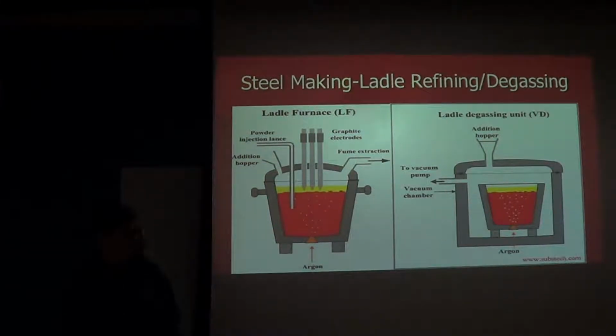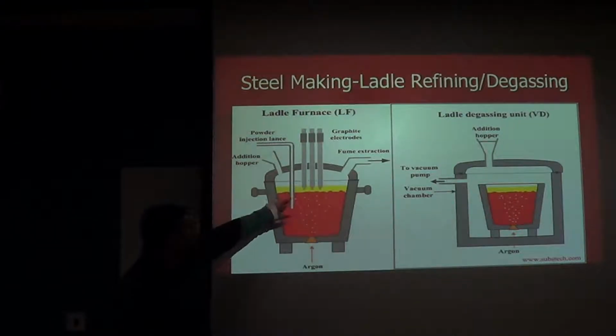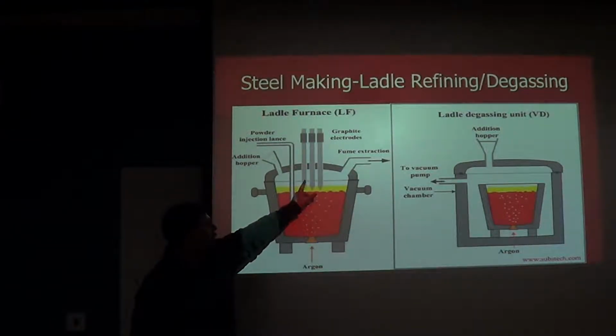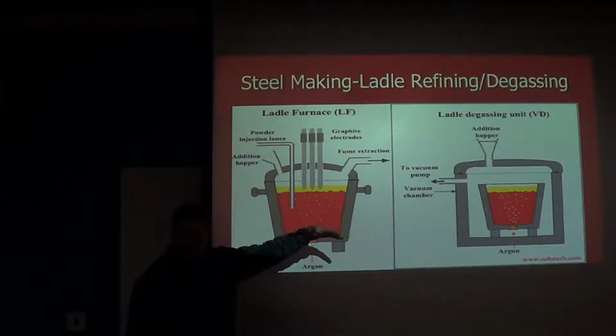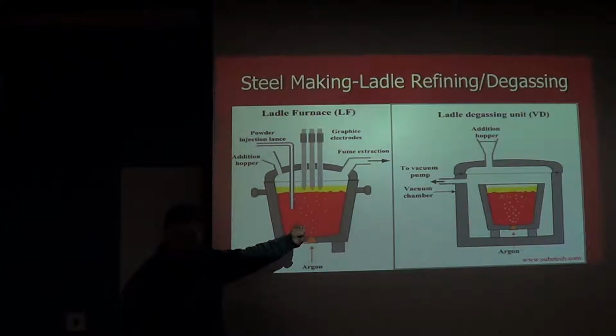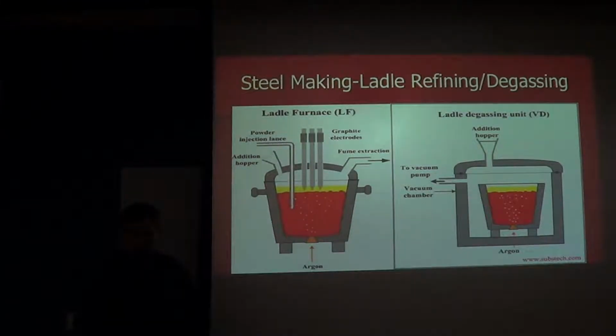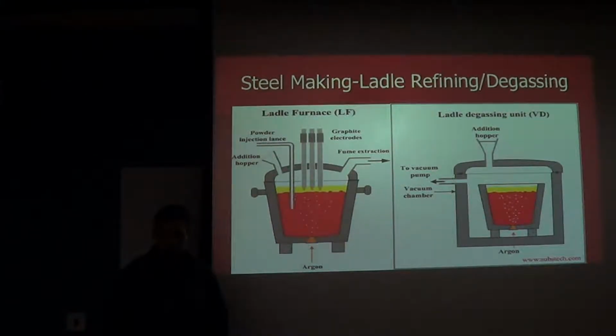Is the first one just to keep it warm while you're doing all the... Here? Yeah. So here, often you'll have a secondary set of electrodes that are used for a little bit of reheating so you don't get too cold. Okay. So you melt in the big arc furnace, you put it into this container, and then they put the lid on, and those electrodes allow it to stay warm while you're doing it. Because we're at like 3,000 degrees now?